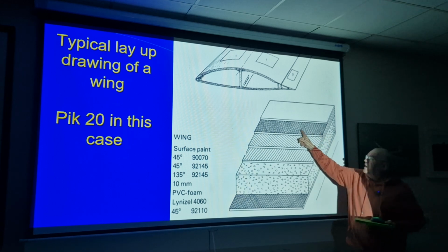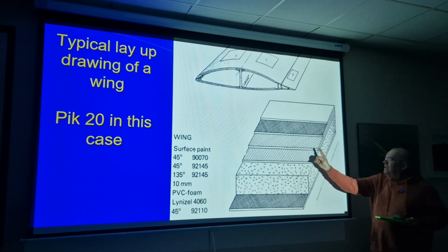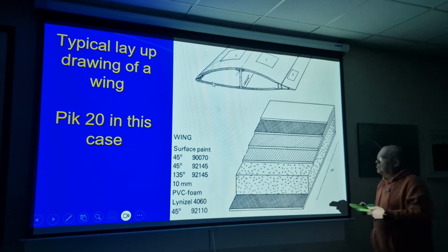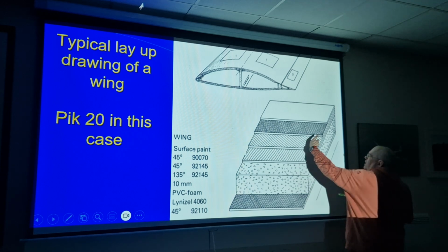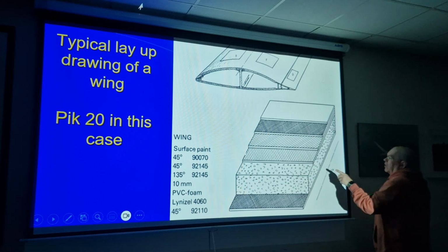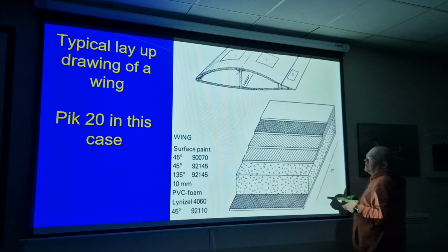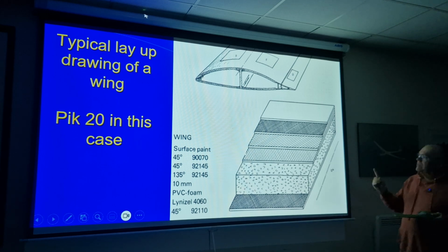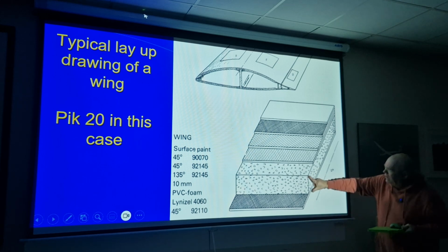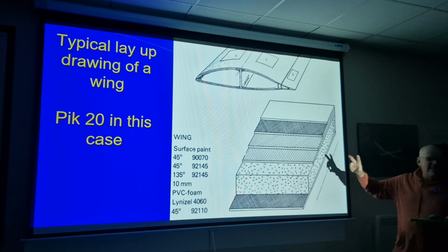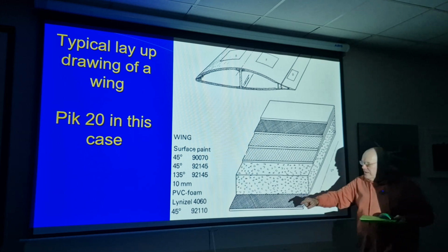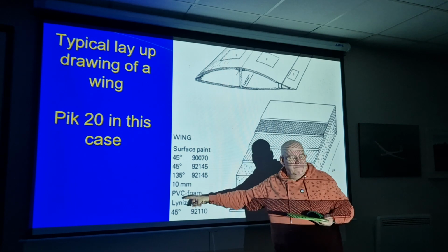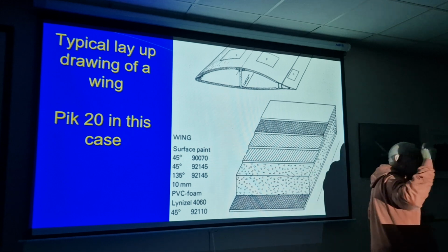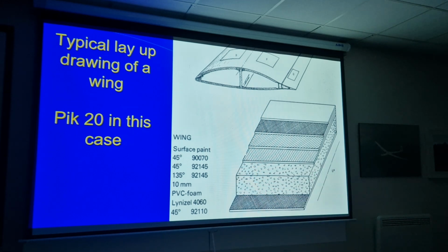It's a really fine layer of glass fibre. And now there's a layer of unidirectional glass fibre going across the wing at a 45-degree angle, and another one going at 90 degrees the other way. Where they're different to most other gliders is the foam core here was a slightly higher density than most other foam cores, and it's 2mm thicker. Most glider wings have 8mm foam cores. This actually has a 10mm foam core. If you have a Puchacz, that has a 6mm foam core.